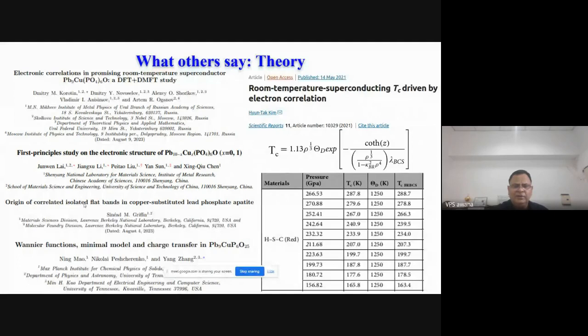Well, what does the theory say? About the theory people, I will not cite all the papers because now some 40-50 papers have come. DFT, DMFT, clubbed DFT and DMFT, and all that. Even Professor Bhaskaran has very nicely explained how an insulator with strong correlations can become a superconductor at the boundary of the insulator-metal transition, which is the case here.